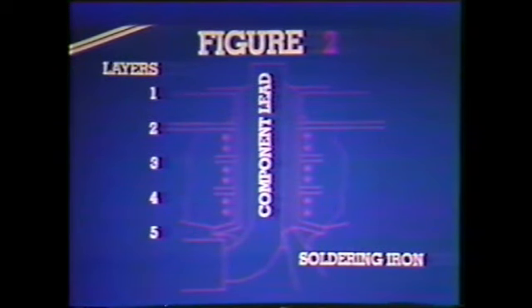If a pad on a multi-layer board is lifted and there are no interlayer connections to the hole, a rivet may be used. If there are interlayer connections, a rivet is not a reliable connection. If a connection has been heated enough to loosen a surface pad, the interlayer connections probably have been damaged due to heat stress in the board material. This is a cross-section of a normal soldered multi-layer board hole, including a component lead. Here's the same hole with heat applied.